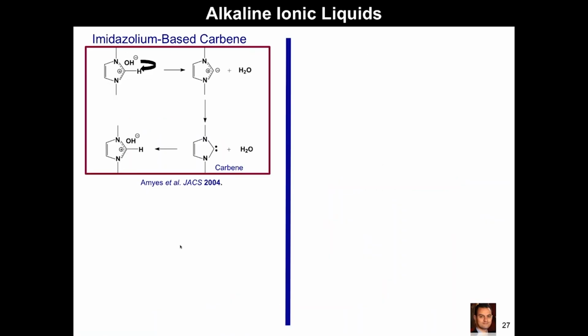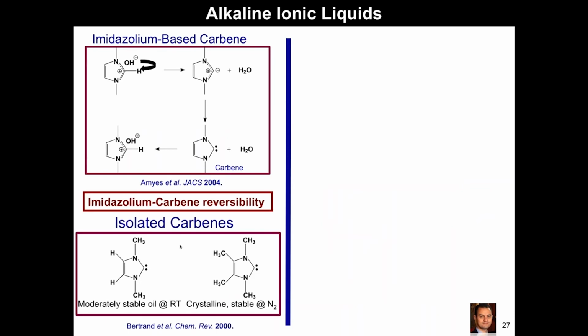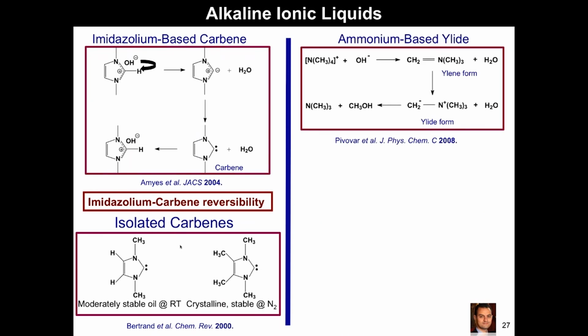We were interested in ionic liquids. And so here I'm just showing you an article that shows the reversibility of the imidazolium when you hydrate and dehydrate it to a carbene. And people have shown that you can isolate these carbenes and they're fairly stable. And this is to be contrasted with the ammonium-based chemistry where if you hydrate or dehydrate, you could irreversibly form ylids.